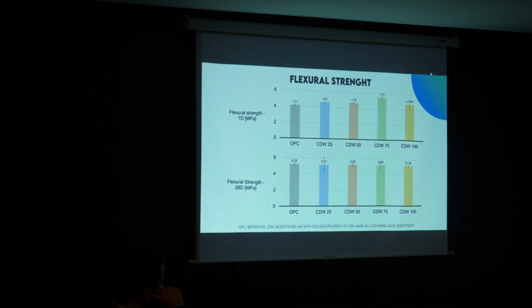After 7 days and 28 days of curing time, the 3-point bending test was performed to evaluate the flexural strength, and it was possible to observe an improvement in the initial phase of the material, arriving at an improvement of around 10%. However, at 28 days after curing, we obtained a steady result. There was a stabilization in this property.